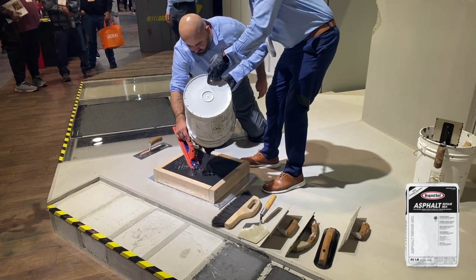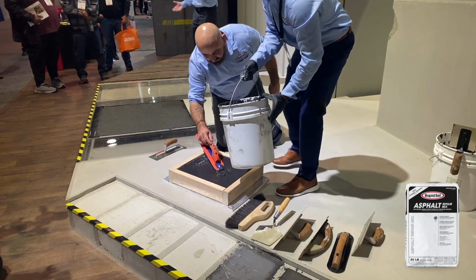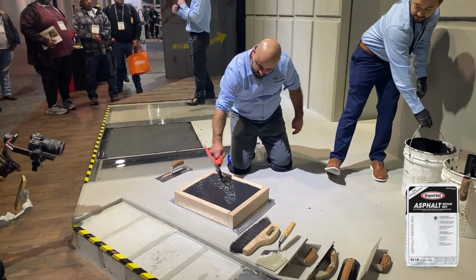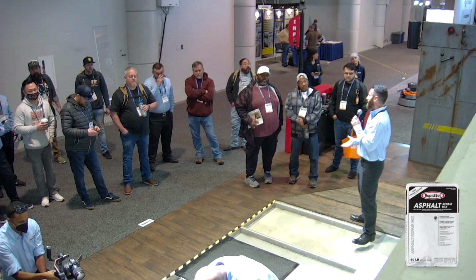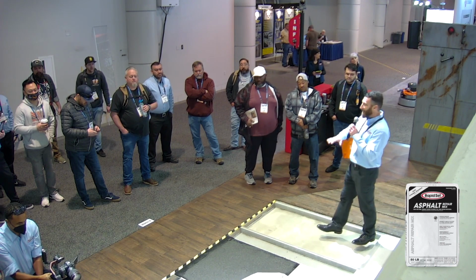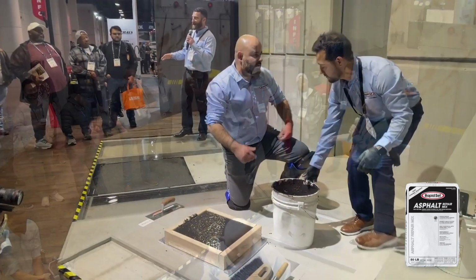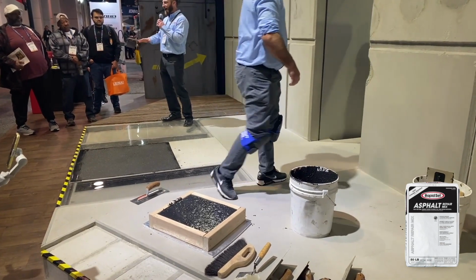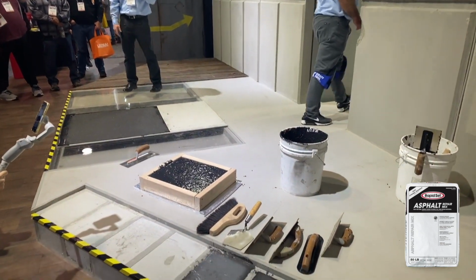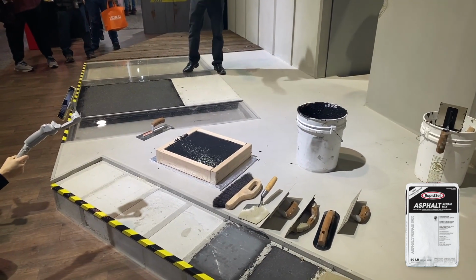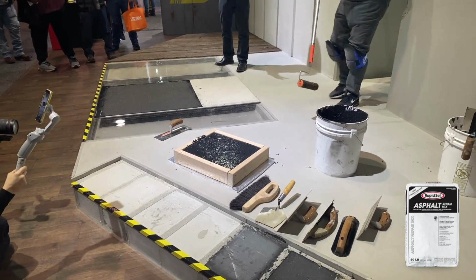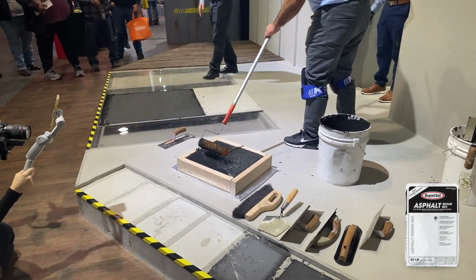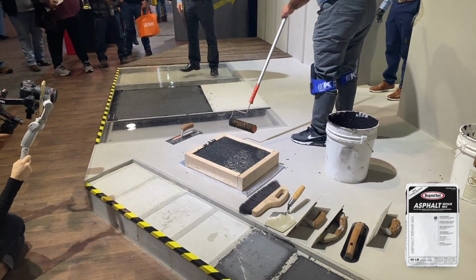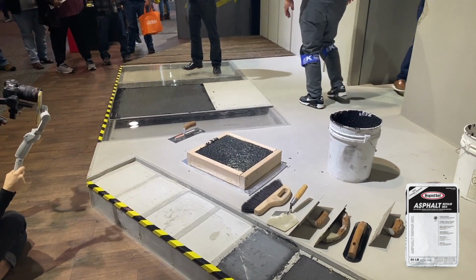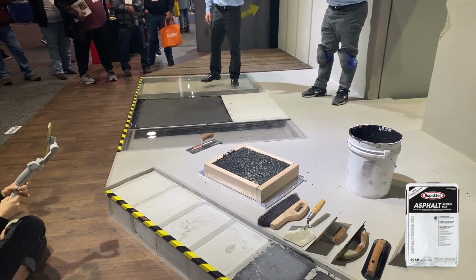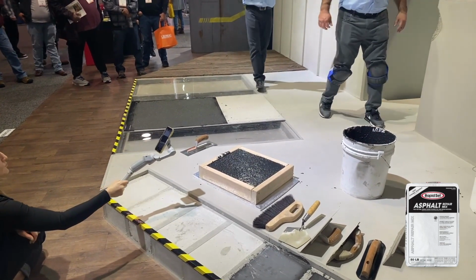Now, if you're familiar with the cold patch type of asphalt repairs, you know they're not very easy to install. You've got to pour them into the hole and then tamp it down. And tamping, I know, is not very easy. A lot of times we'll either leave the cold patch too high, and so it's not flat, or maybe we can get it flat, but then it will subside and shrink into the hole over time. With the asphalt resurfacer and the asphalt repair mix, because they're based on cement, they can just be troweled smooth, troweled flat, and it's not going to shrink or subside into the hole over time. So both these products have excellent adhesion to asphalt, and they're durable as well. So they'll be around for years to come.